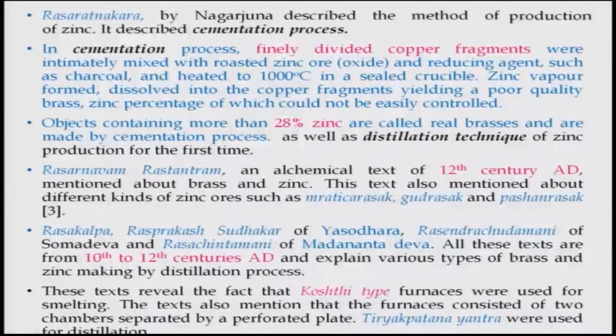And these texts reveal that Koshthi type furnaces were used for smelting, and the texts also mention that the furnace consists of two chambers separated by a perforated plate, and Tiryakpatana yantra were used for distillation. If you look at it, there is a lot of literary evidence for the zinc distillation technique and also the cementation process for making zinc.